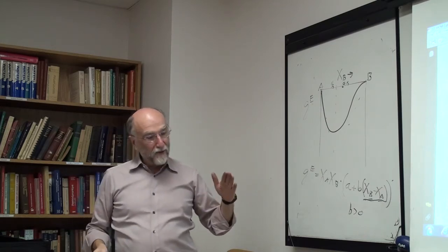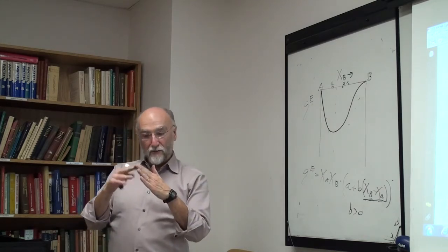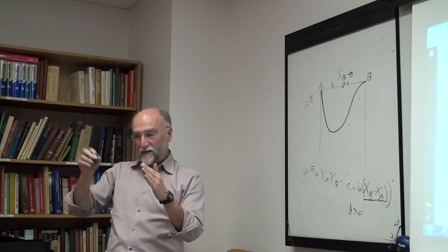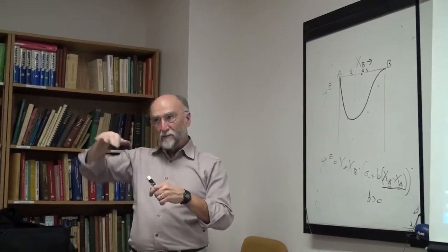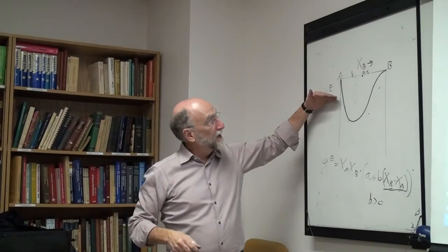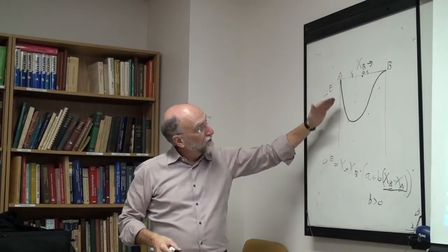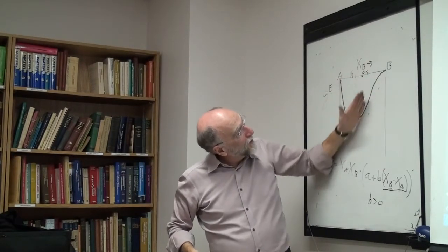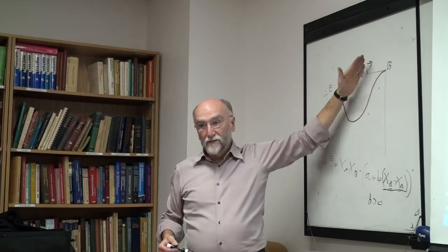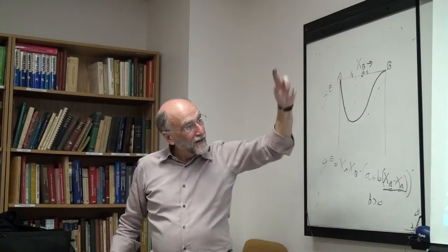Remember the other day I talked about a ternary term, x1, x2, x3, where I can give you positive on one side, and even if your term is positive, you can end up with a negative partial. The same thing can happen here. You're trying to move the curve over here, and you end up on this side giving yourself a positive excess Gibbs energy, you can't get around it.